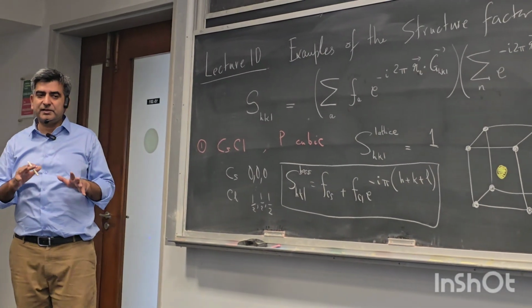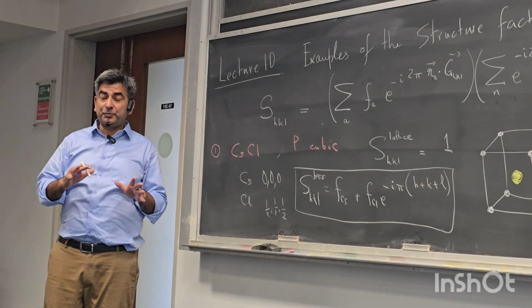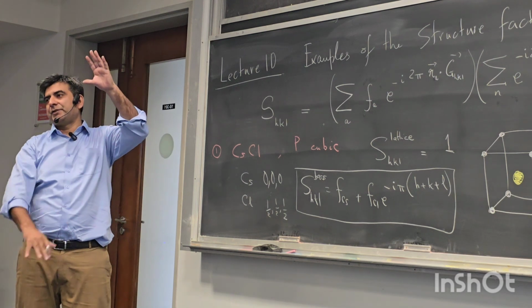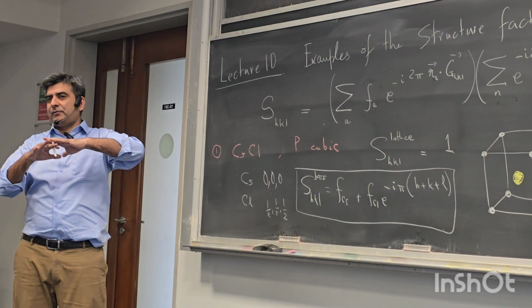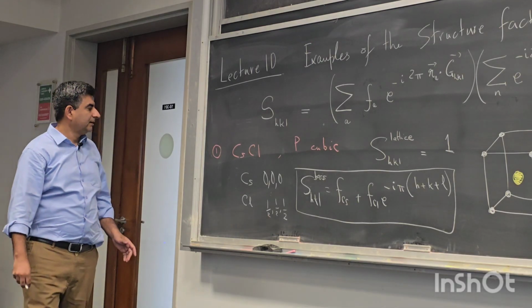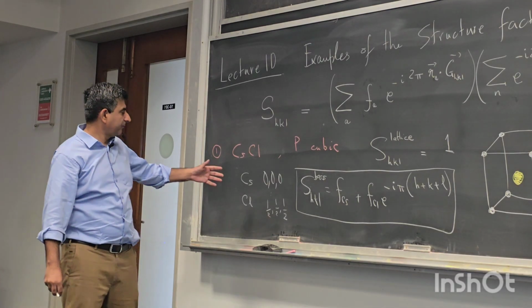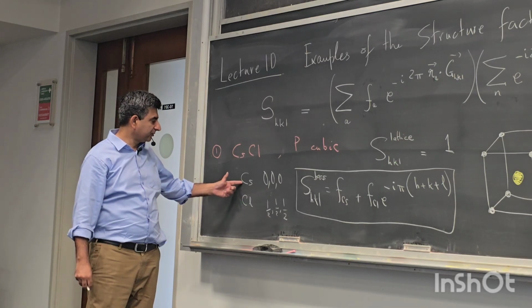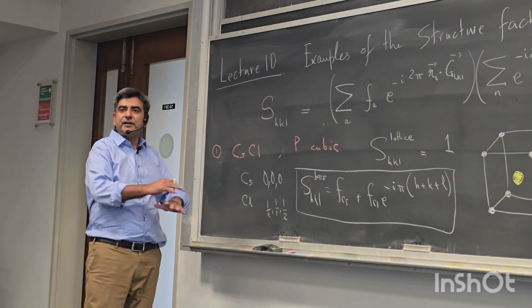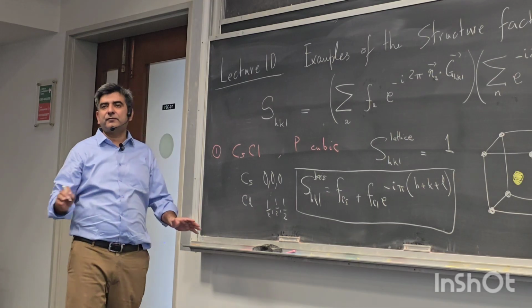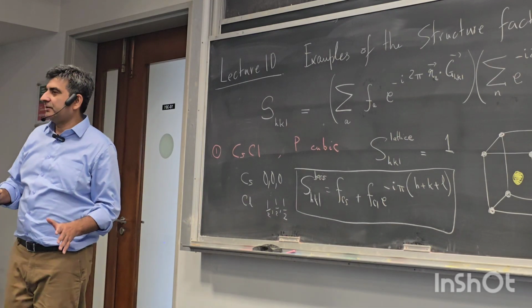So if you look at the group tables, at the extreme right you have reflection conditions. For cesium chloride, for primitive cells, you look at the Wyckoff positions which correspond to cesium and chloride, and you will find out there are no reflection conditions. All kinds of planes can reflect.